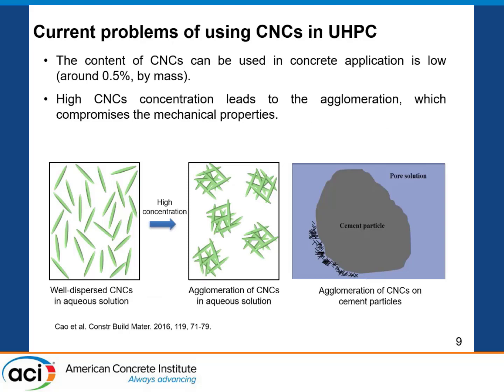However, by just directly adding the CNCs into the system, there are some problems. If you use lower amounts, the CNCs are hydrophilic, so they can disperse well in a water solution. But if you use a little higher, higher than 0.5% by mass of cement, then severe agglomerations will be observed, and that compromises the mechanical properties.